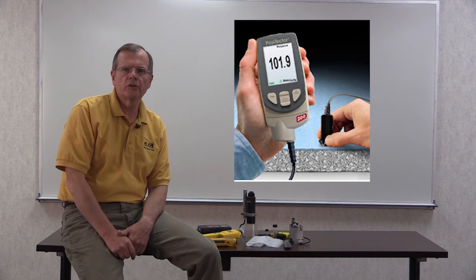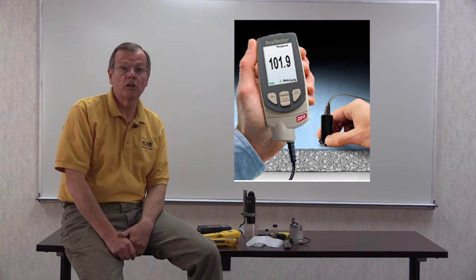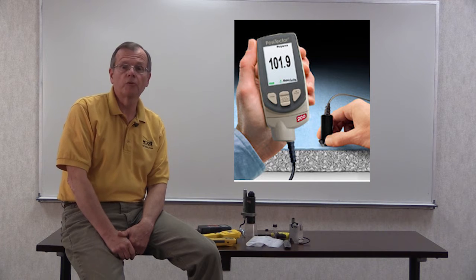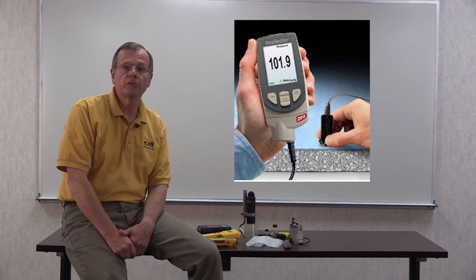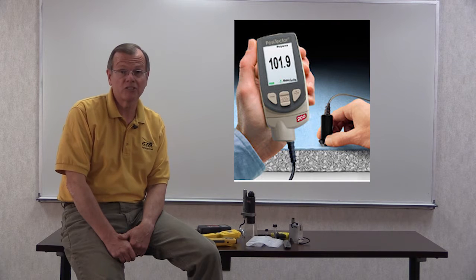The total thickness of a coating system on a concrete floor can be measured non-destructively using an ultrasonic thickness gauge. But when doing forensic work, it's often important to know the thickness of the individual layers. The ultrasound gauge is not capable of doing that. In addition, if there are air voids entrained in the coating, or lamellar pigments such as glass flake in the film, an ultrasound gauge may produce false thickness readings.